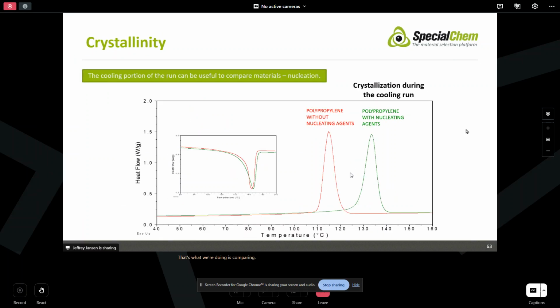Now, in the condition of the material, we've talked mostly about the melting endotherms, okay? But let's not look past those recrystallization peaks, because they do tell us something. Again, here's an example of polypropylene with and without a nucleating agent. So a nucleating agent might be used in polypropylene to impart some clarity, okay? Maybe make your potato salad container that you get at the deli so you can see through it, okay? It changes the way the crystalline structure forms. And we can see that there's a pretty big shift in that recrystallization. Now, there wasn't a big difference in the heat of fusion or the melting point of those two resins, but there is a big difference in how they form crystals because of that nucleating agent.